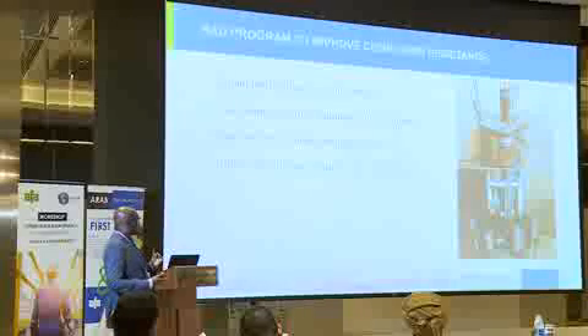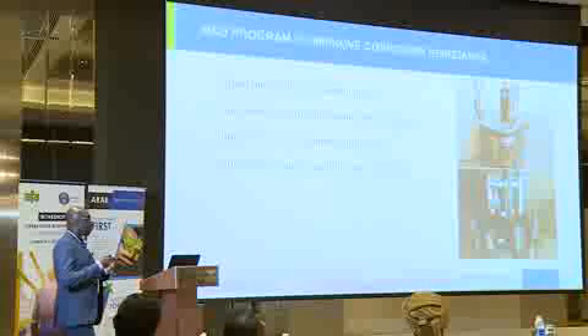And then the other thing that we wanted to do differently from what was done in the 90s was that we wanted to test in the exact condition or as close as possible. So for generation 1 of Safurex, so the Safurex that was developed in the 90s, they developed it using standard tests like Huey test and Streicher test. But we decided that we will take the composition that you find in a stripper tube and recreate it in the laboratory using this titanium autoclave over here, and test our alloys together with Safurex, and then choose the composition that outperforms Safurex. Second thing is the temperature here is quite high, higher than you would find in a stripper, and also it's zero oxygen. So the conditions that we tested in are much more severe than you'll ever have in your plant.